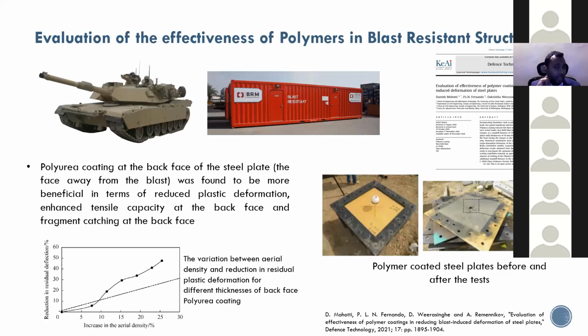Another way of enhancing the effectiveness of, say, steel to resist blast is actually using polymer or polyurea. So there was another experimental program where polyurea coated steel plates were tested for the same blast setup. We did a set of tests with polyurea at the front of the plate and then polyurea at the back of the plate. Having it at the back of the plate was more effective for the reasons I've given here.